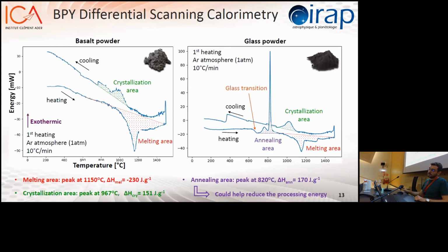We have also conducted some differential scanning calorimetry. For those who are not familiar with this technique, the point is to have a sample on which we apply a temperature program. Here we are heating until 1,500 degrees Celsius and then cooling back. What we monitor is the heat flow going in or out of the sample, because every time you have a phase transformation, it will be either exothermic or endothermic.